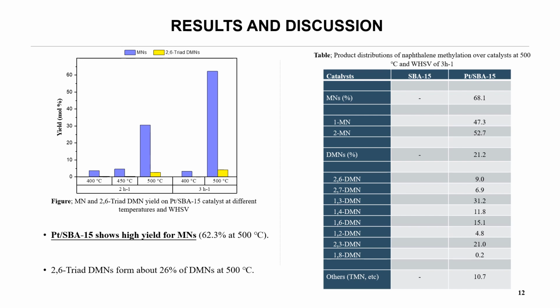In addition to high selectivity for 2,6-dimethylnaphthalenes, PT-loaded catalysts showed high yield for methylnaphthalenes at higher temperatures. As mentioned previously, methylnaphthalenes are also important starting materials for 2,6-dimethylnaphthalene synthesis. As can be seen in the product distribution on PT-SBA-15 at 500 degrees Celsius on the right, 68.1% of methylnaphthalenes as product is achieved. Furthermore, the more desirable 2-methylnaphthalene isomer is produced in contrast to 1-methylnaphthalene. The distribution also shows high amount of dialkylated products compared to undesirable tri- and tetraalkylated naphthalenes.